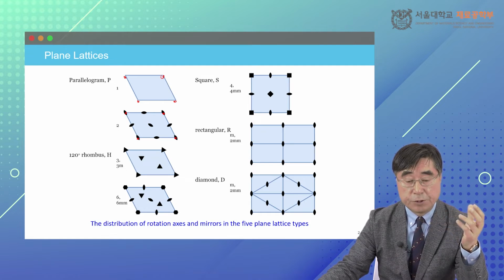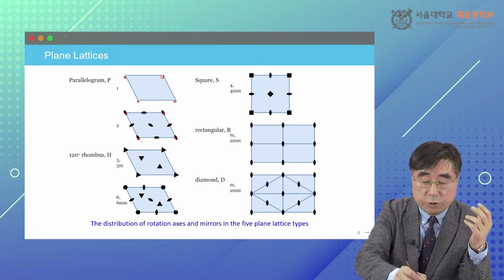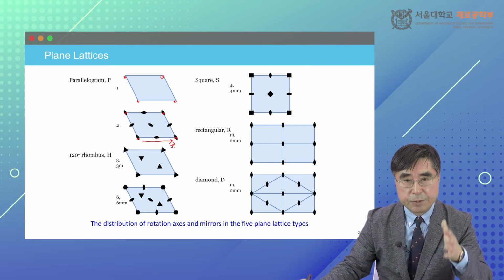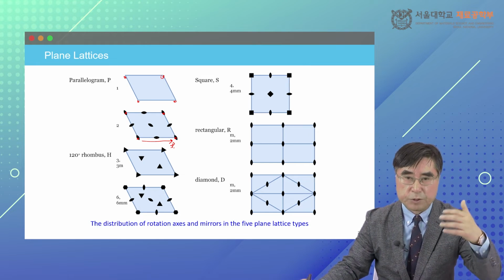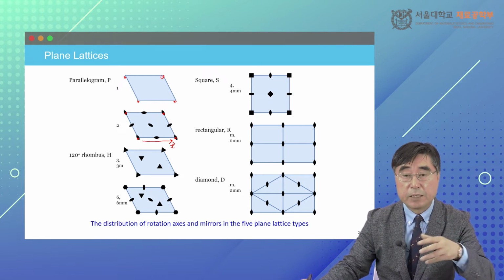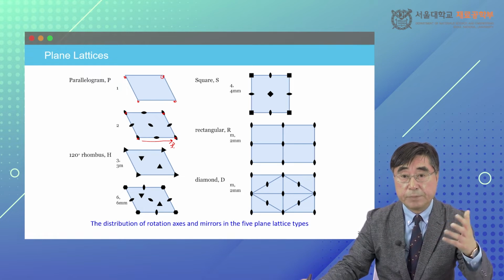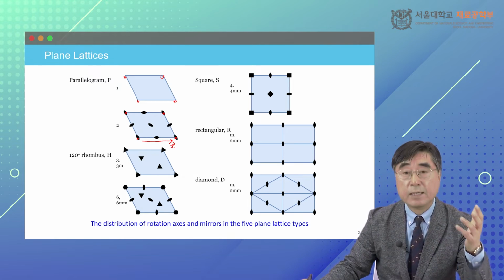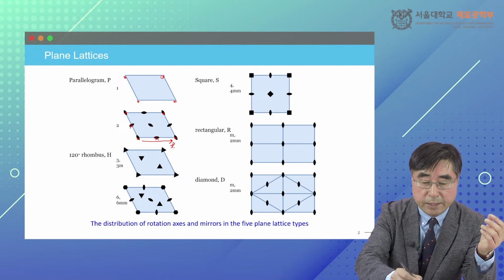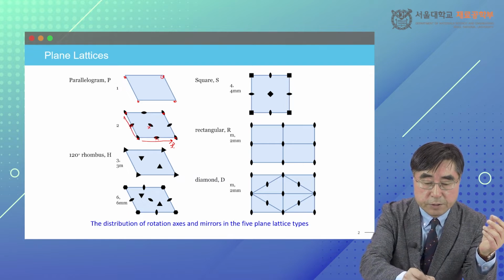Last time I explained to you that when there's a two-fold symmetry here, and there is a translation vector, then along the bisector lines, at half of the t vector magnitude times cotangent alpha divided by 2, the same two-fold symmetry is generated. In the two-fold case, extra two-fold symmetry is developed here and here and here, based on the translation vectors of t1 vector and t2 vector.